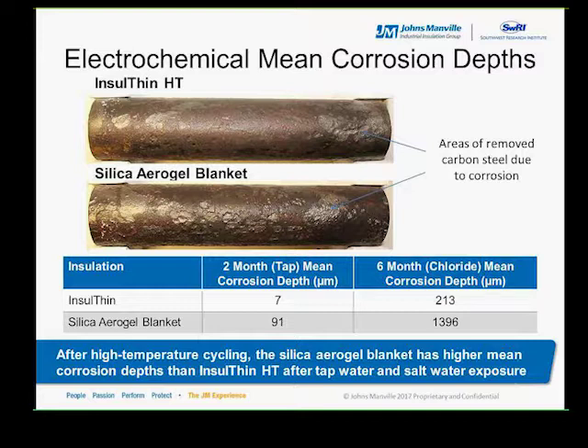The data in the table shows an order of magnitude difference in the mean corrosion depth after both the solution exposures and times. So after the 2 months of tap water exposure, the mean corrosion depth was 7 microns for the Insulthin versus 91 for the aerogel blanket. This difference increased to 213 microns for the Insulthin and almost 1,400 microns for the aerogel blanket after the 6 months of 1,500 ppm chloride exposure. The difference in corrosion depth is also seen in the pictures, where the silica aerogel blanket has much more corrosion pitting on the surface of the pipe than the Insulthin blanket specimens.